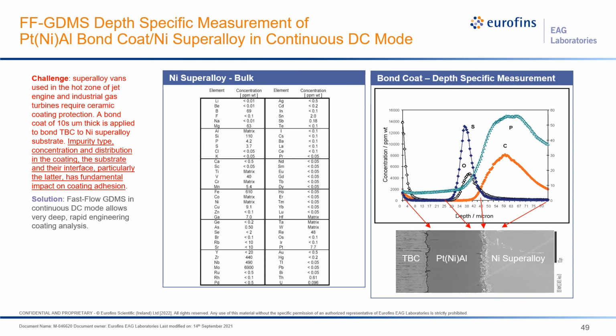The second part of information we give you will be the bond coat and the nickel superalloy interface information, which will allow you to identify what kind of impurities are there and where they are located. In this case, you can see there is enrichment of sulfur and oxygen from the interface of the bond coat to the nickel superalloy substrate.